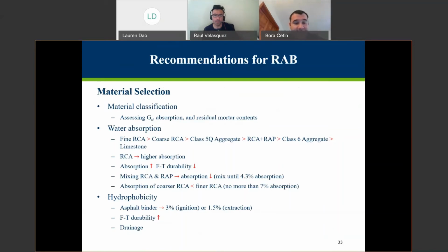Based on this study, we suggest, not hard line, that absorption value may be limited to 7%, so you don't want to go above 7% absorption for the pure RCAs, and mixing RCA rep will decrease that absorption value. But again, based on the data that we collected, we may suggest that you keep that absorption value below 4.3%.